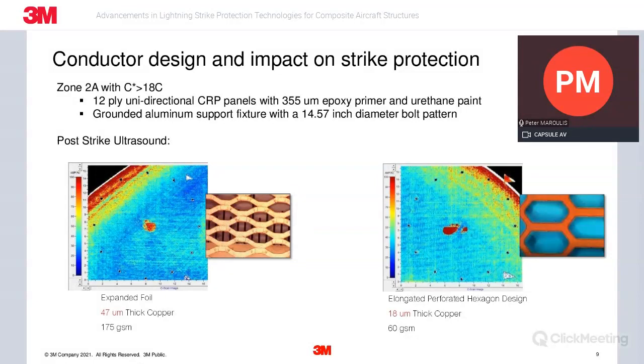In this slide, you will see two images of a Zone 2A strike. This is a 12-ply unidirectional composite prepreg underneath. The panel on the left has an expanded copper foil conductor with a weight of 175 grams per square meter. The dots show where the system has been grounded, and you could see the damage from the strike. On the right, the panel has a perforated copper foil conductor with a weight of 60 grams per square meter. It has a hexagonal perforation design, and you could see the damage is quite similar in size with the image on the left.